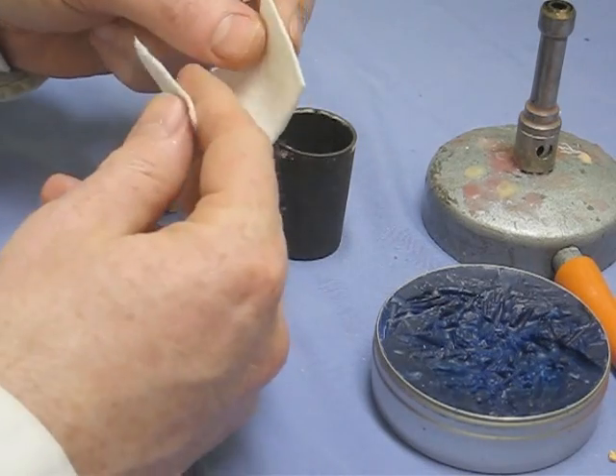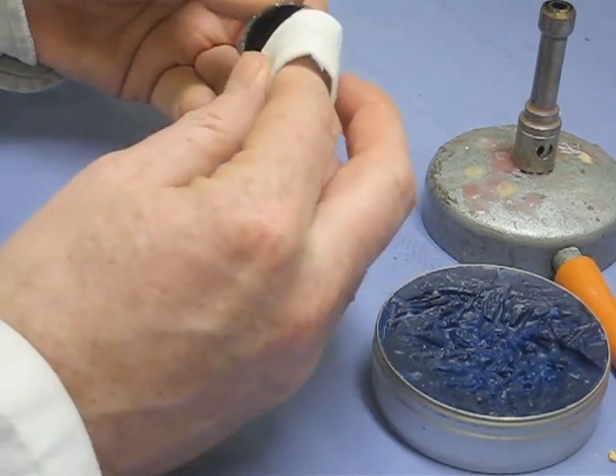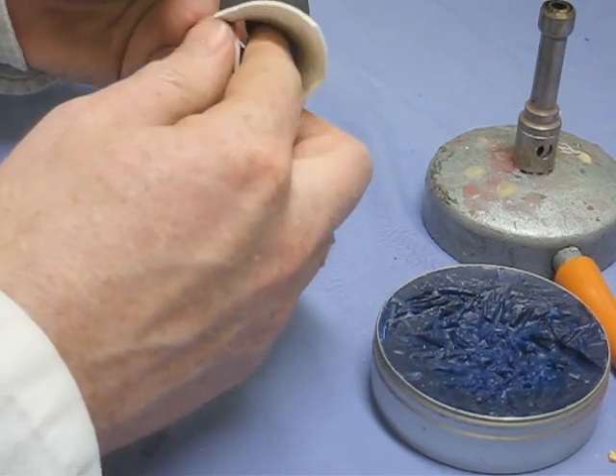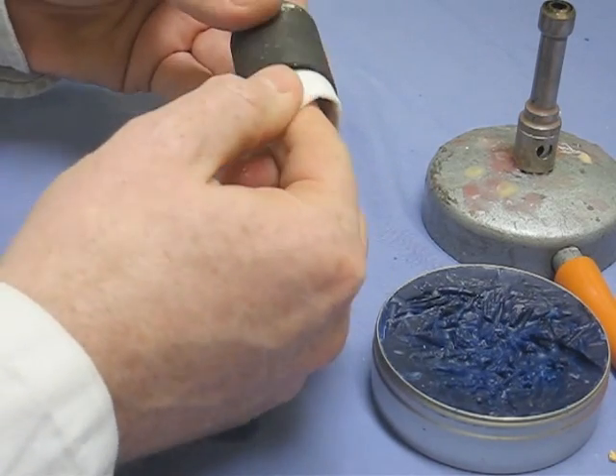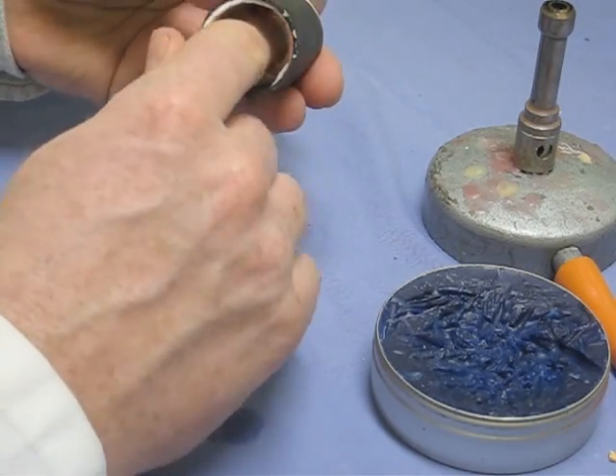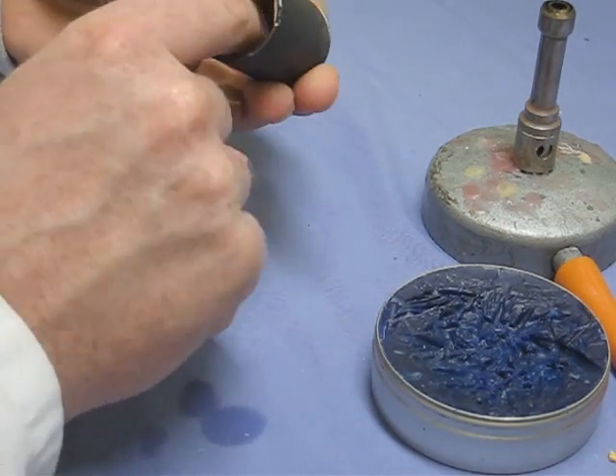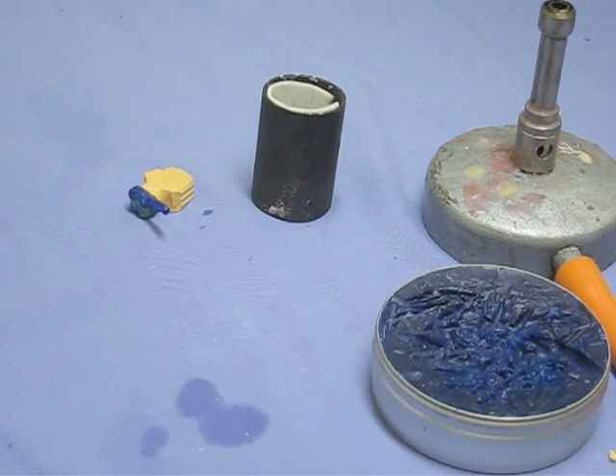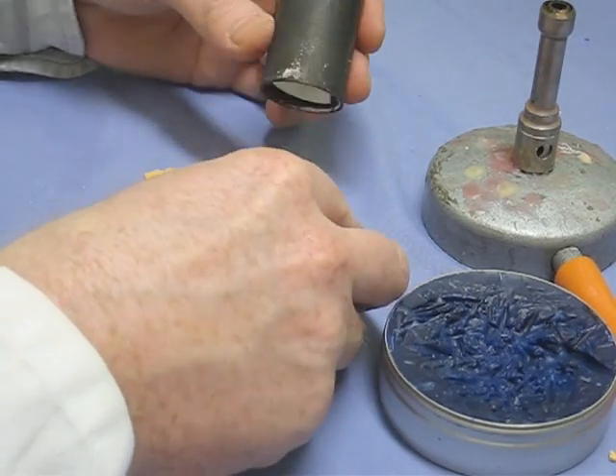This is the casting ring and the ring liner. That allows the refractory material to expand as we're heated up in the furnace. Those of you who remember your materials maybe will know that the silica based material expands rather suddenly over about 600 degrees C.